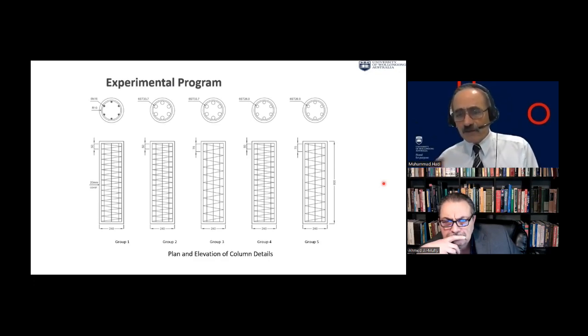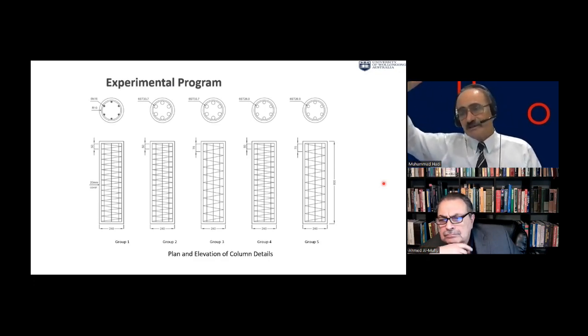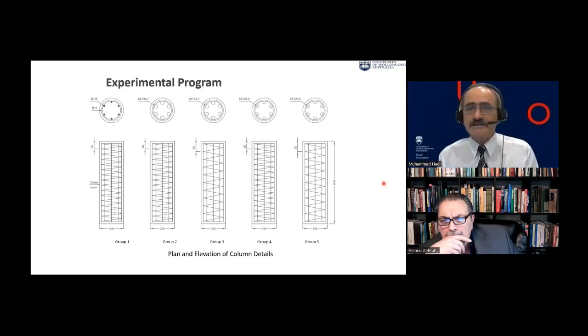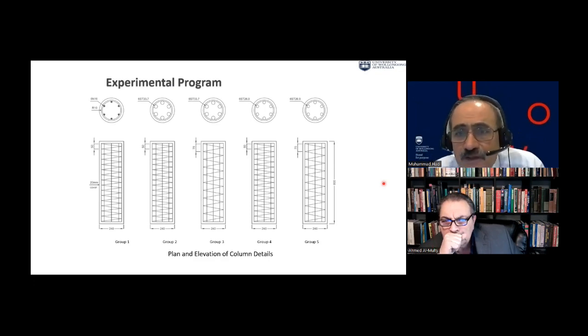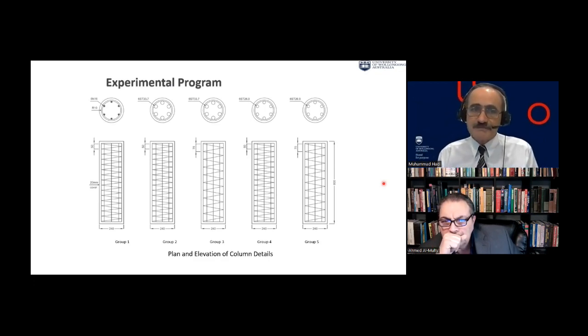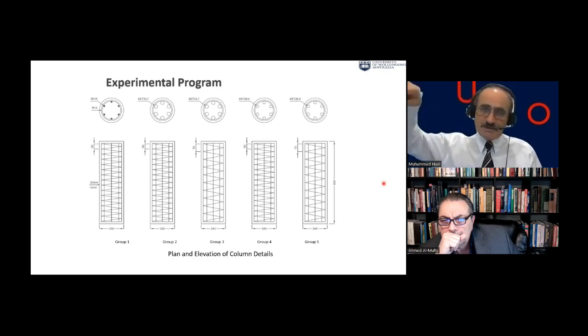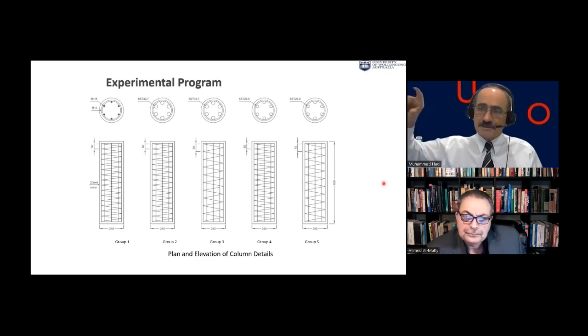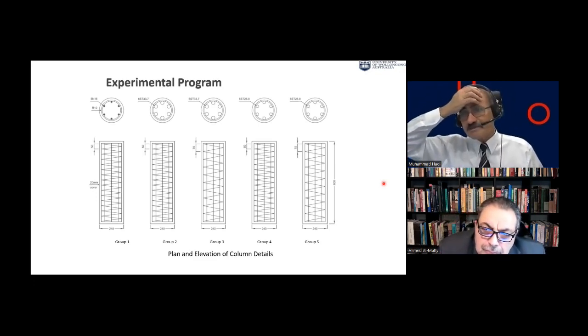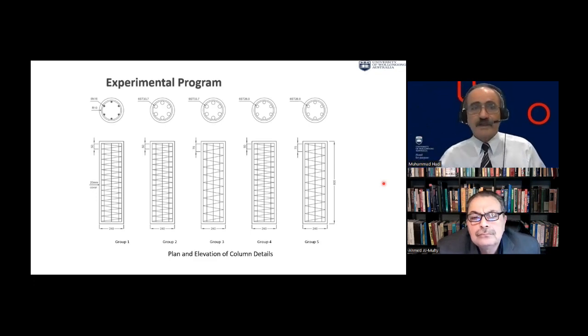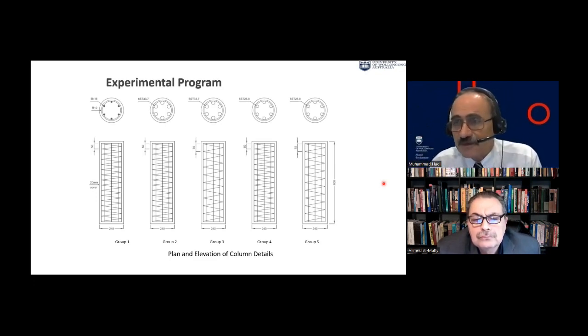Okay. Now here we did the testing. Now these testing I'll show you. Because of our compression machine, 500 ton, it is about 1 meter, so we don't test more than 800 mil. So we said, okay, let's test those in 5 groups of specimens. The first group is just reference specimen. And here we have the N16, 6 of them, and then R10. R10, this is the 250 plain bars for helix. And R10 spacing 50 mil.